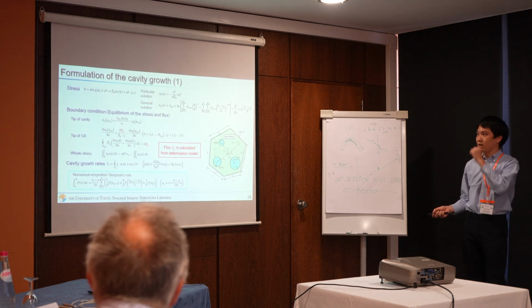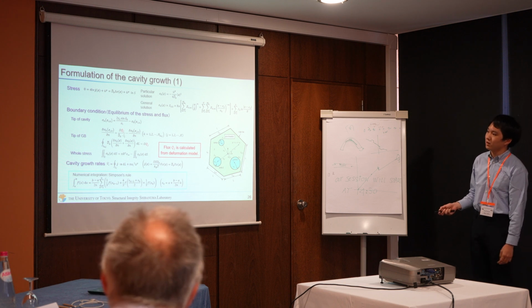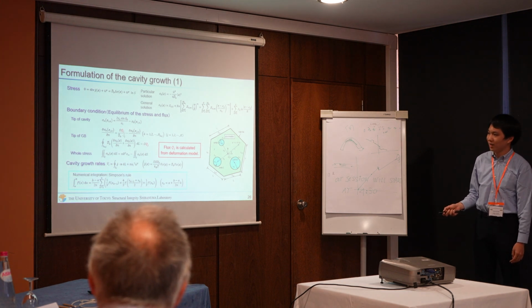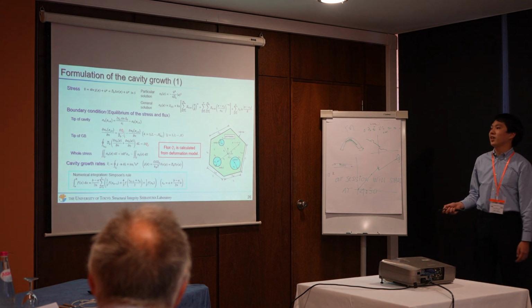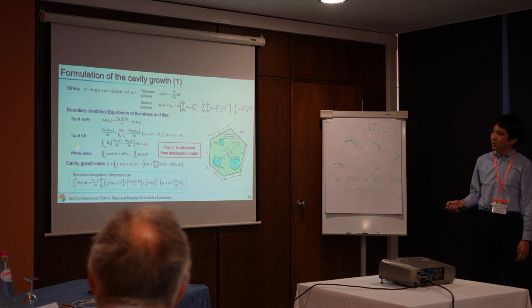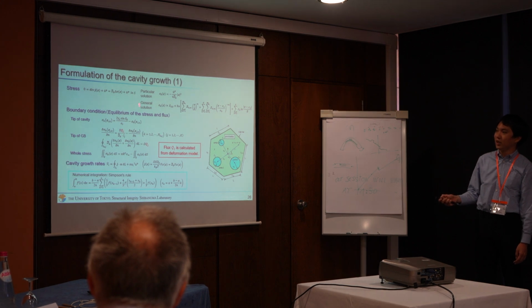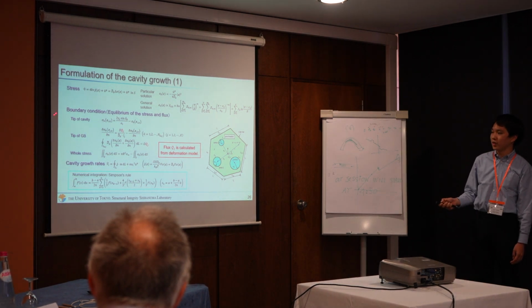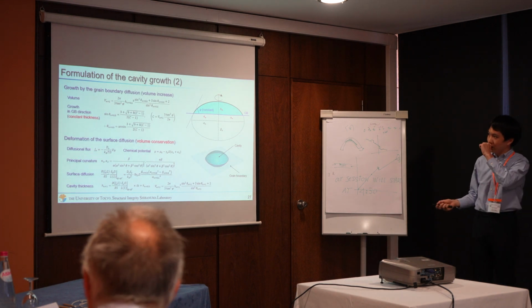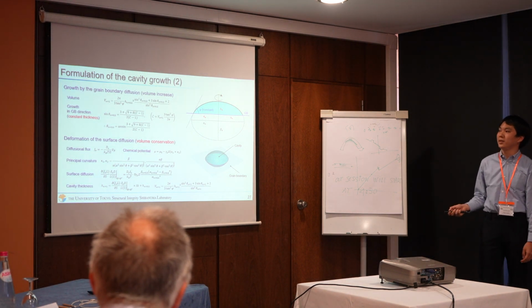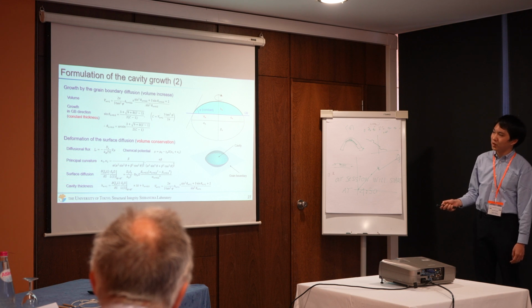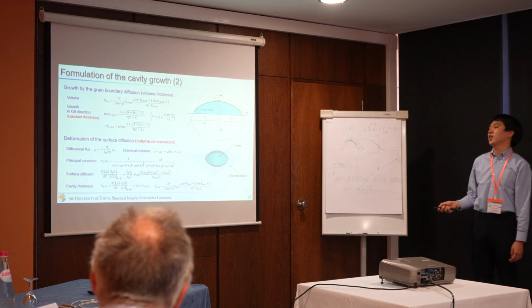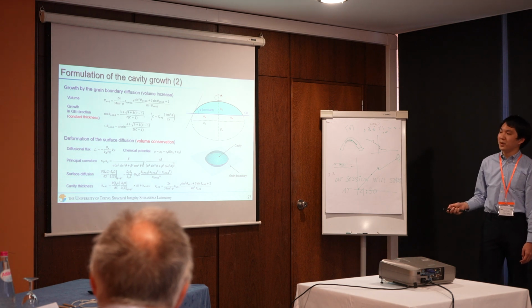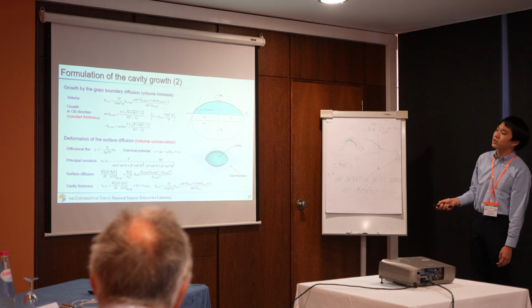And this is the formulation of the cavity growth. The function that calculates the stress at each point is found by this differential equation with these 4 boundary conditions. And this is also the formulation of the cavity growth. First, due to the grain boundary diffusion, the cavity grows only in the grain boundary direction. And next, due to the surface diffusion, deformation occurs as the volume is conserved.